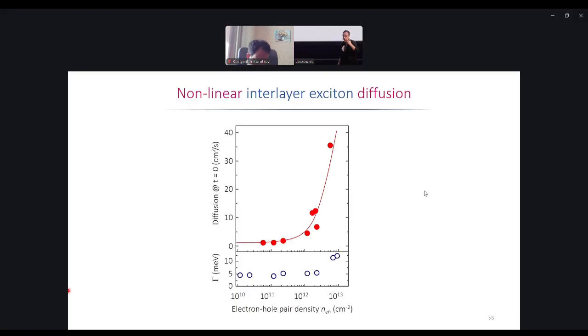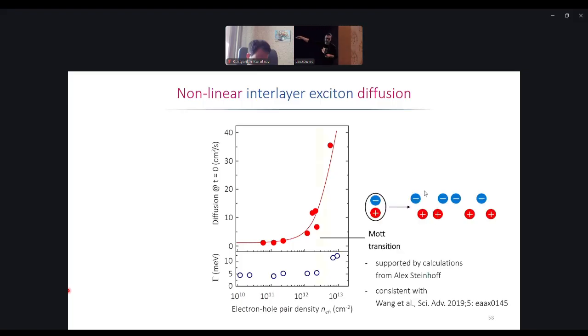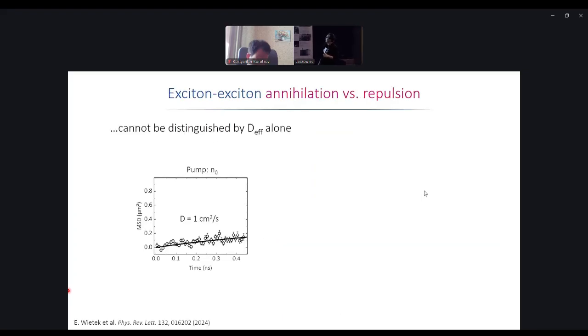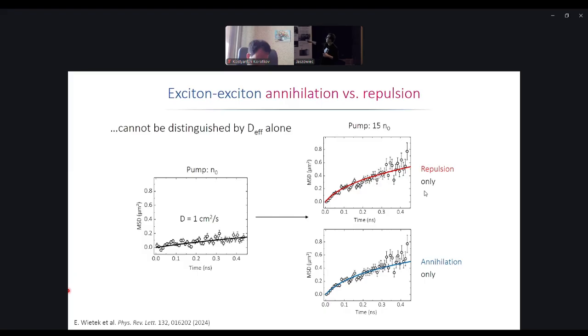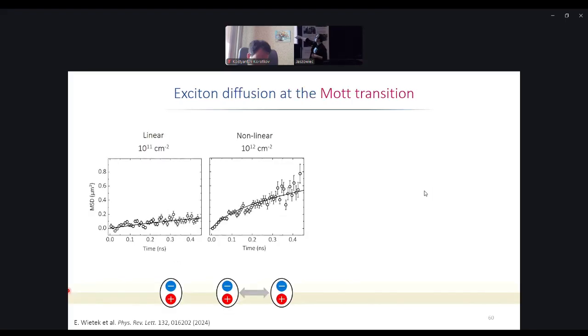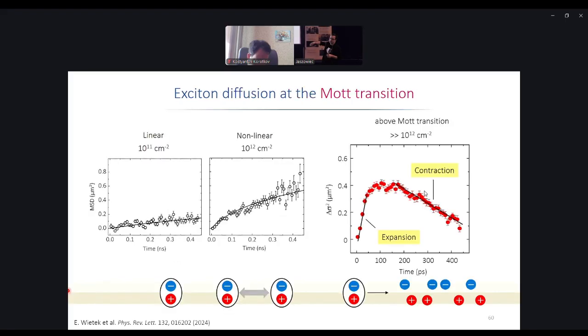And regarding the nonlinearity, also here, one can see that the effective diffusion coefficient will increase with density. At some point, there is even a Mott transition, which is a little bit harder to determine accurately, at least in luminescence experiments. And one thing to consider is that in this case, if one just looks at the transport, just at the broadening, one cannot distinguish whether it's repulsion or annihilation. One needs to make additional analysis, actually properly count the excitons in absolute terms in the spot. And finally, one can have weird effects here as well, at the Mott transition, expansion, contraction. But I would stop here.